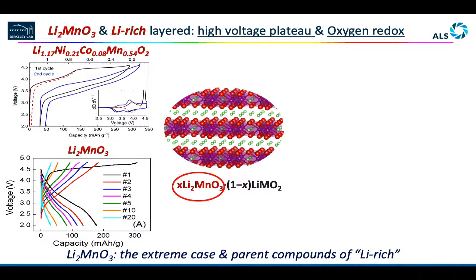So if we look into this material, on the first question I posted on the material origin of this oxygen redox, what we have over here, the reason you have more than 1 lithium in the compound is you mix this so-called parent compound of Li2MnO3 in here. So if you mix this with a conventional lithium-1 transition metal oxide, that's how you introduce that. And if you look at particularly this parent compound, what it has is the lithium is taking 1/3 of the layer of manganese. So the lithium getting into the transition metal layer, that's why you get more lithium in there. So lithium in the Li2MnO3 is the reason this material is called lithium-rich. And lithium-rich is the flagship material to discuss the oxygen redox.